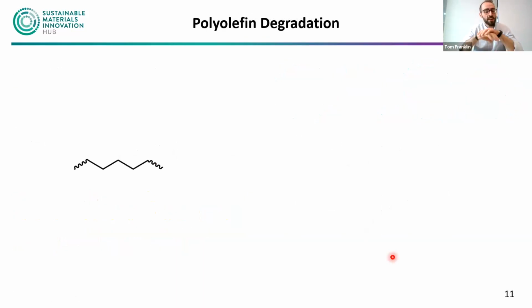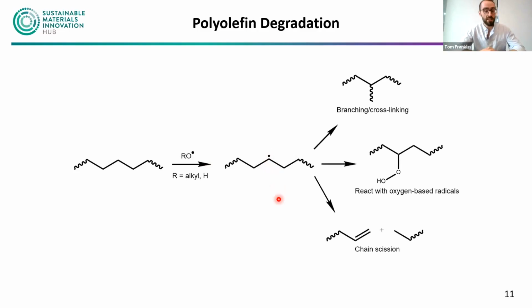So just to give you a brief overview of what actually happens, we take our polymer chain, shown here. Something, whether that be the heat or the shear or the oxygen, will generate what's known as a radical, which is this species here, typically very reactive, and in this case it will react with the polymer chain, and it will take a hydrogen atom and transfer the radical behavior to this chain. So we now have a very, very reactive radical chain, and this is a largely self-propagating reaction. Once you have radicals present, they can be quite hard to contain, quite hard to control.